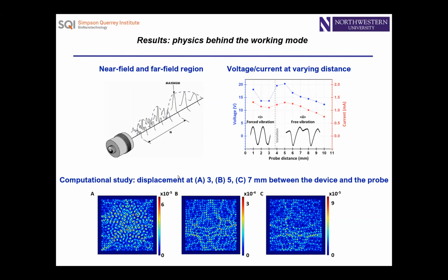We also checked with a computational study, which agrees with our experimental result. The simulation result shows that the displacement at 5 millimeters is the highest, which originates from the maximum pressure level.